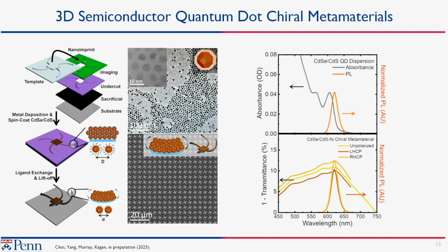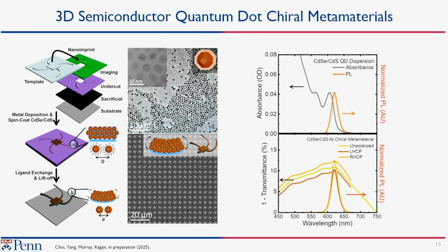If you take these structures and look at 1 minus the transmittance, which is similar to the absorbance, what you'll see is that if we shine unpolarized light, it's the curve in between. These structures happen to be right-hand circularly polarized, which we use to consistently compare. We see something a little bit larger that comes from the excitation side. You can also see something that we think is related to photonic modes riding over the top of this spectrum. And obviously right-handed is greater than left-handed in the extinction.